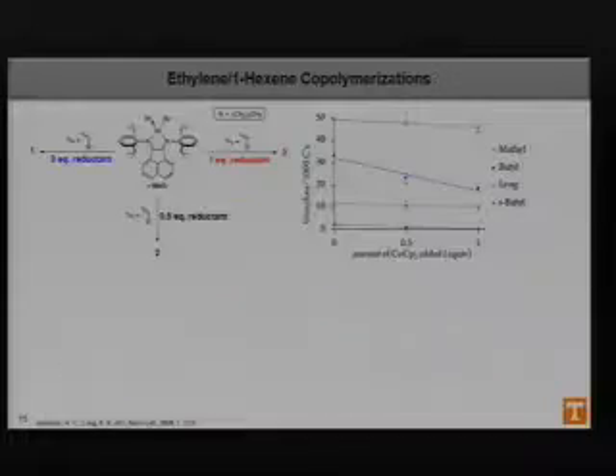So we ran 3 separate trials where we added 0 equivalents of reductant, half an equivalent, and then a full equivalent for the copolymerization of ethylene and hexene. And we found that, again, we saw a decrease in branching as we increased the equivalents of reductant. And specifically, the decrease for butyl branching was much, much larger than the others, which would make sense if the hexene, which should have 4 carbons other than the 2 that are involved in the backbone, was being incorporated less.